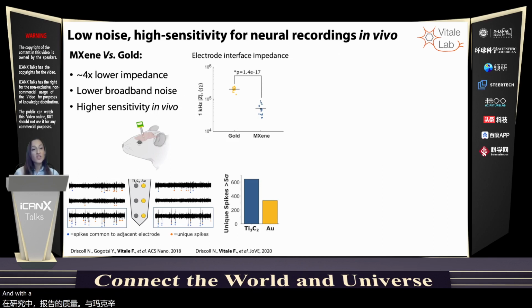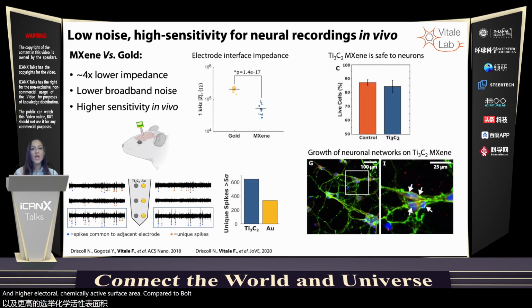And with additional characterization, we attributed the superiority of MXene to both its higher capacitance and higher electrochemically active surface area compared to gold. Importantly, in the same study, we demonstrated for the first time that Ti3C2 MXene is safe to neurons and actually can support healthy neuronal function and growth.